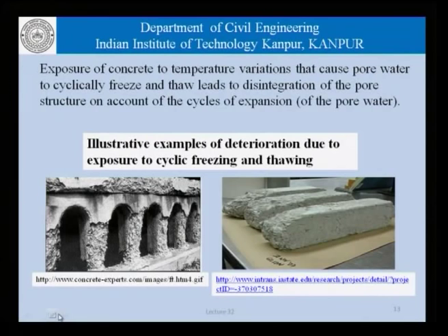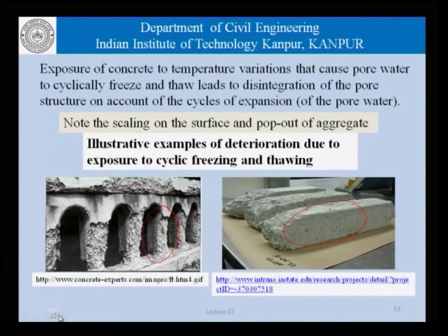These here are illustrative examples of deterioration on account of exposure to cyclic freezing and thawing. We can see here, whether it is this structure or these beams which are specimens tested in the laboratory, that there is a lot of disintegration in the pore structure and also pop out of aggregate.